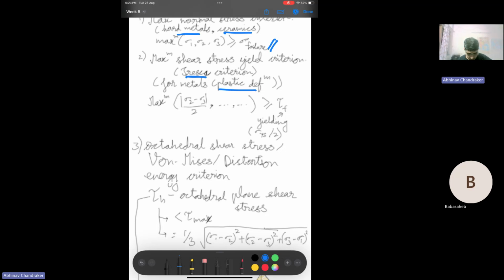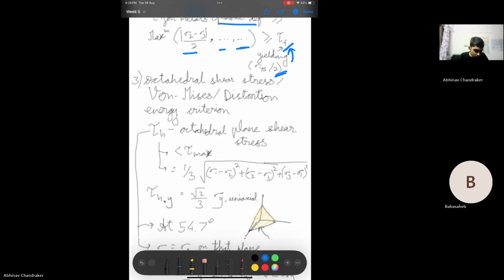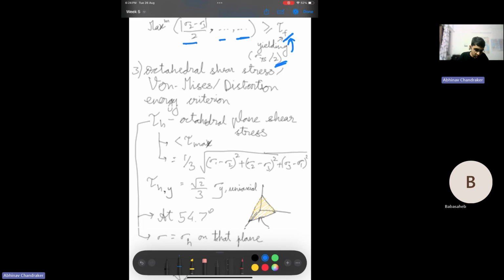In this case, we look at the shear stresses on the three different planes. What are the maximum shear stresses? And the maximum one among them should be more than a particular threshold value for failure to occur. And this value will be the value which you will get if you are loading just uniaxially. And that, if you calculate, will be sigma ys by 2. So in a uniaxial tension test, the maximum shear stress is sigma ys by 2. You can very easily find that by using a Mohr circle. So this is how you compare between a complex stress state and a uniaxial loading stress state and come up with these criteria.